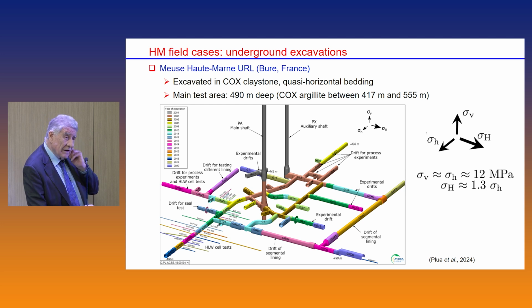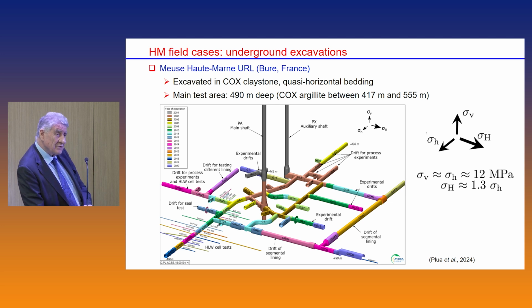This is the layout of the lab. What is important here is the in situ stresses which occur in the lab. First of all, there is a vertical stress which is more or less equivalent to overburden. And the horizontal stresses are not isotropic. There is a major one, which is about 1.3 the vertical stress, and a minor one, oriented at 90 degrees, obviously, which is quite similar in value to the vertical one. So, and very nicely, Andra excavates the galleries in the direction of the major and minor principal stresses horizontally, which actually helps with interpretation.